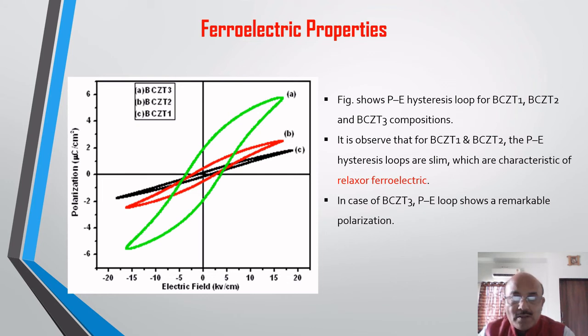Now if we observe this graph, for BCZT1 and BCZT2, the P-E hysteresis loops are very slim, which is a characteristic of relaxor ferroelectrics. And for BCZT3, the loop shows a remarkable polarization. So BCZT1 and BCZT2 are relaxor ferroelectrics.